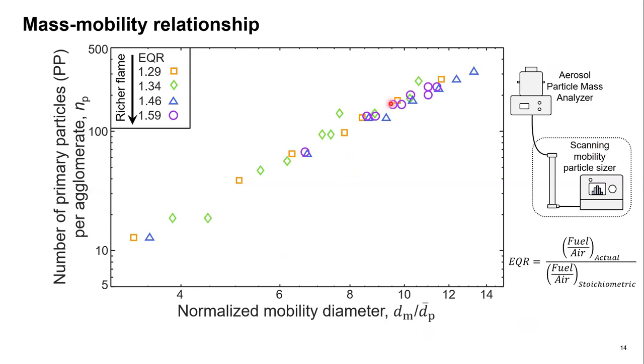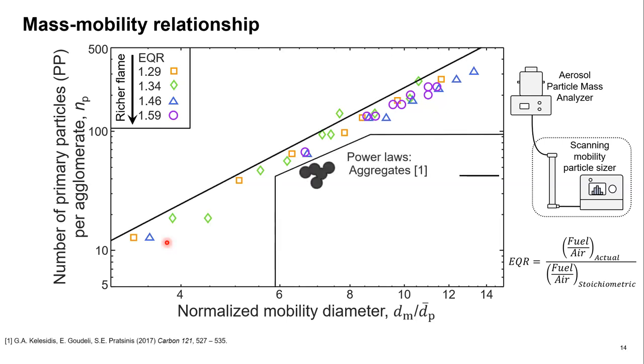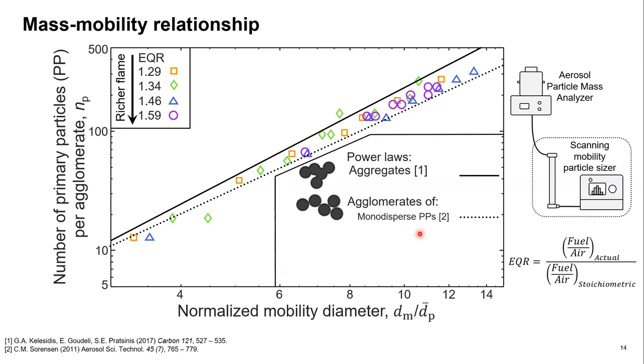What we see is that all of the data fall in approximately the same line, so we do not see any significant difference in the mass mobility relationships between the different equivalence ratios. But to better understand this, we can look at how this compares to the theory. First, I have this solid black line showing a theoretical power law for aggregates, also known as hard agglomerates. Here, the primary particles are strongly fused together through necking and strong chemical bonds. On the other extreme, we can also have agglomerates of monodispersed primary particles, where the primary particles are weakly bonded together just in point contact.